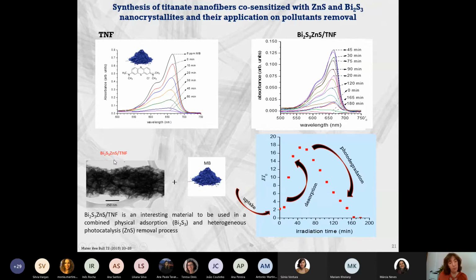we need to think that bismuth sulfide is a very good adsorbent, especially for cationic species. So when we put this material in contact with the solution with the dye, we remove almost all the dye from solution, and then we can take the modified material to the lamp system. We put it in water and we turn on the lamp. So we have degradation of the dye. At the same time, we have adsorption from solution. And of course, here we start to have more degradation than adsorption.